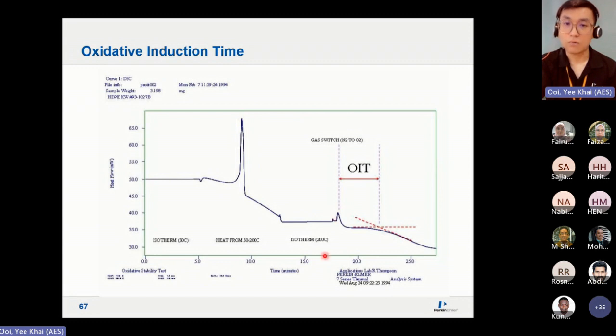Then at 200 degrees C, switch over to oxygen and observe until the exotherm, because oxidation is also exothermic and irreversible. So for oxidation induction time, we take the time from the point that you switch over to oxygen to the point where the exotherm comes out. This is how long it takes for your material to get oxidized.